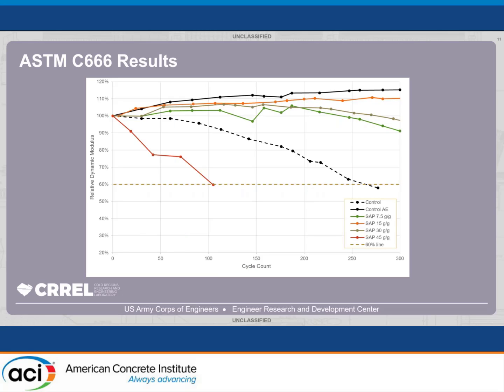Moving forward into our freeze-thaw testing results, this was, again, ASTM C666. The way this test is measured is that all specimens at the very beginning, before they're put into the chamber, are measured for their relative dynamic modulus. Once they reach 60% of their original, they have failed. If they continue to stay where they are, they'll go until it's been 300 cycles of freezing and thawing.